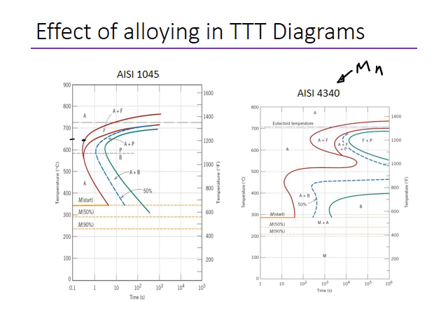But now that you are adding manganese, transformation starts at maybe 300 seconds. So from 1 to 300. That's a really big change. So by adding other elements to your steel, you can control how fast transformation takes place.